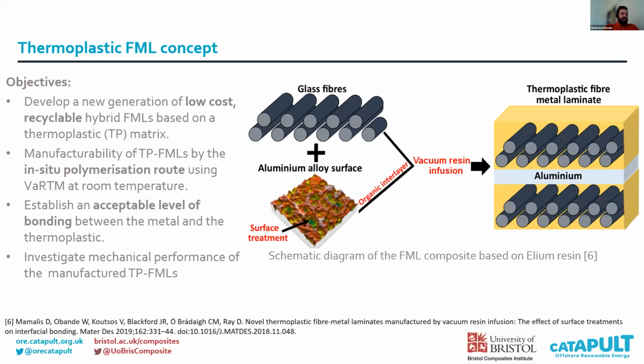So the objectives of this project were to first develop a new generation of low-cost recyclable hybrid fiber metal laminates based on a thermoplastic matrix. Second, manufacturability of these thermoplastic FMLs by the in situ polymerization route using a vacuum-assisted resin transfer molding technique at room temperature. Third was to establish an acceptable level of bonding between the metal and the thermoplastic matrix. And finally, investigate the mechanical performance of the manufactured thermoplastic FMLs. You can see here on the right side the schematic drawing of this approach.